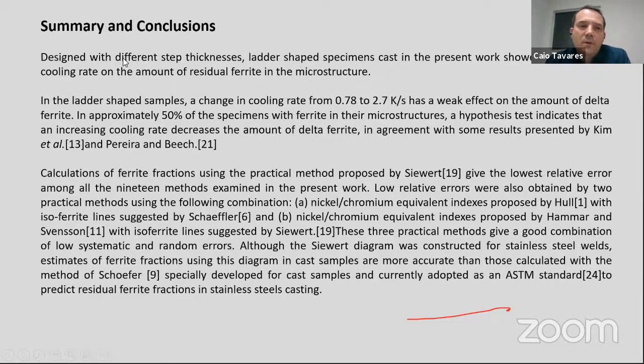So our conclusions here were: we made different step thicknesses to show the cooling rate and the amount of ferrite in the microstructure. We see that those samples have different cooling rates, but they have a weak effect on the amount of ferrite. And we see that in 50% of the specimens with ferrite in the microstructures, the hypothesis indicates that increasing cooling rate decreases the amount of ferrite. It is in agreement with some results presented by Kim et al. and Pereira and Beech.